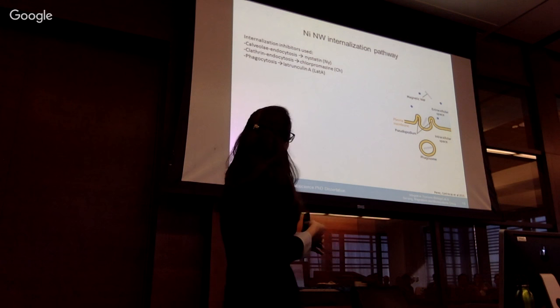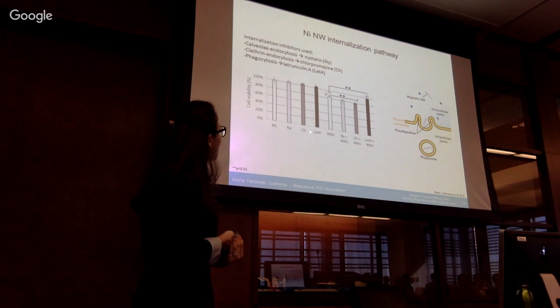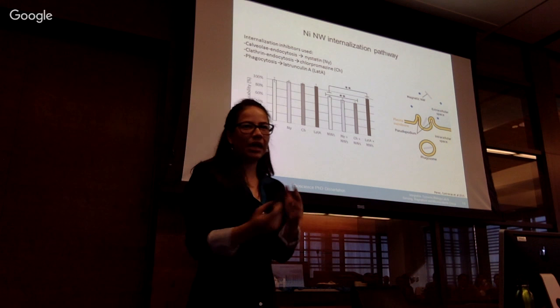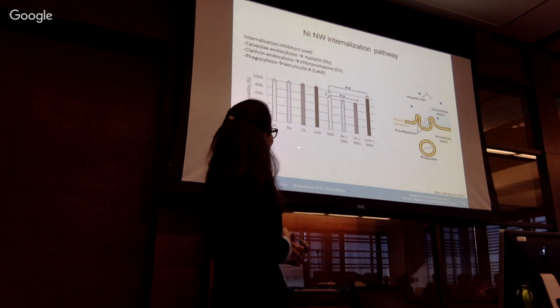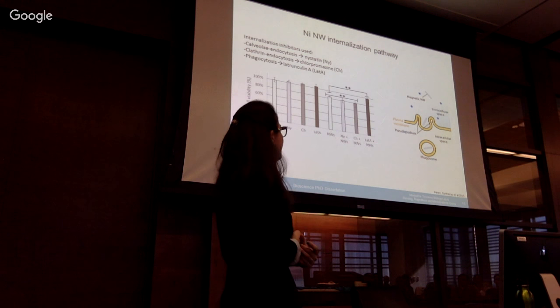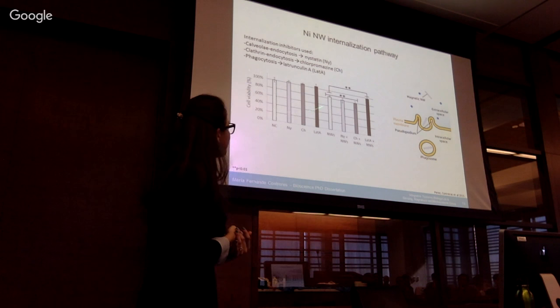So the principle here was as follows. We measured viability, and in these first four bars, we have our negative control and the three inhibitors, just to make sure the inhibitors themselves didn't affect the cells. And we didn't at the concentration used. And then these four other bars resemble these conditions, but here nanowires were added. So we know when we add nanowires to cells, the viability is decreased, as shown here.